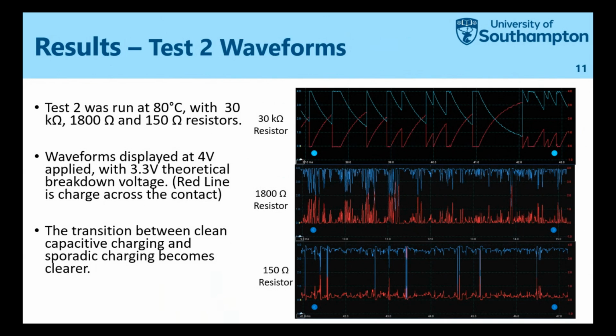You can see that as the resistor value decreases, the current increases, and the cleanliness of the signal decreases. You get an increase in internal resistance, and the insulating properties of the oil become much more difficult to establish for some reason - that's why I've described it as sporadic charging for the high current scenario.